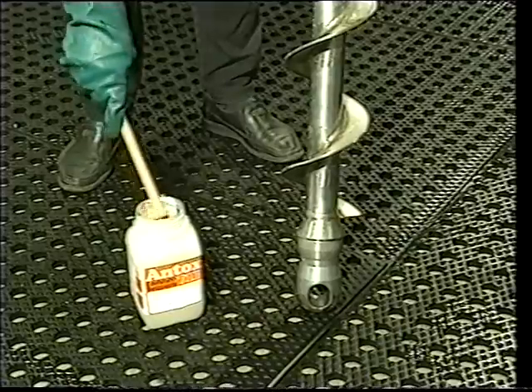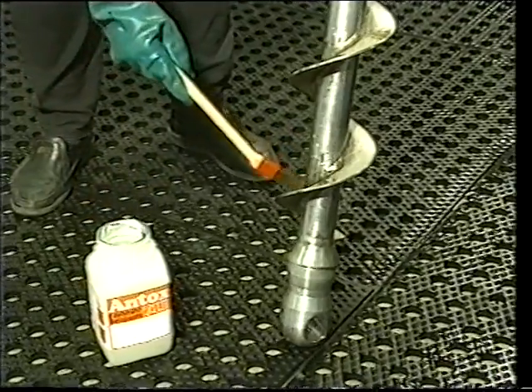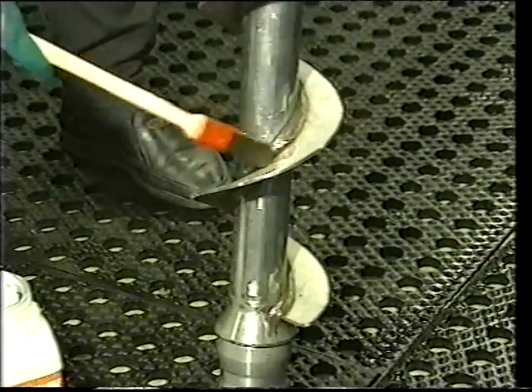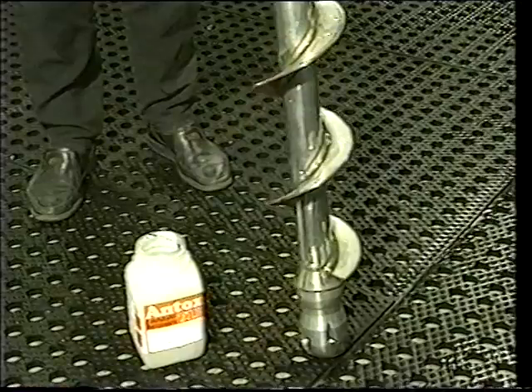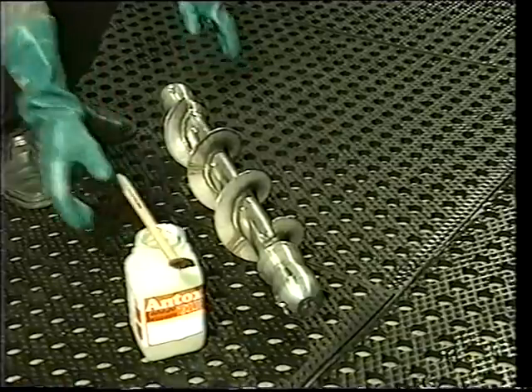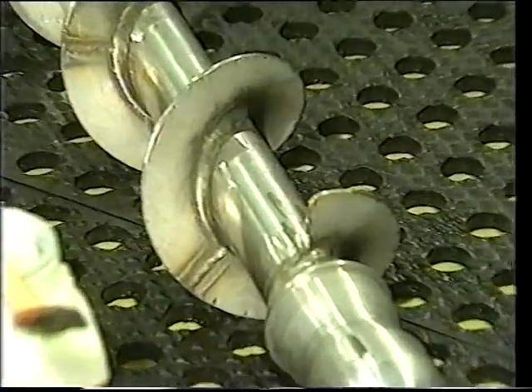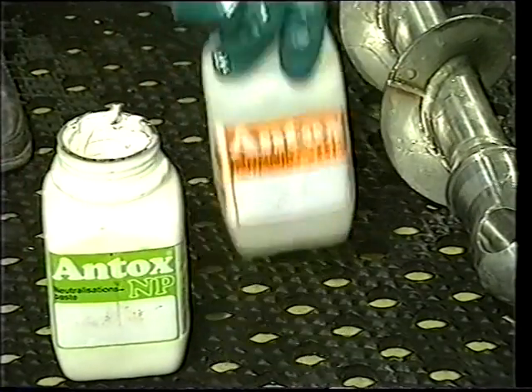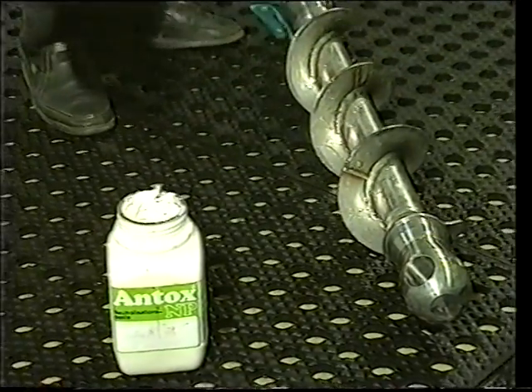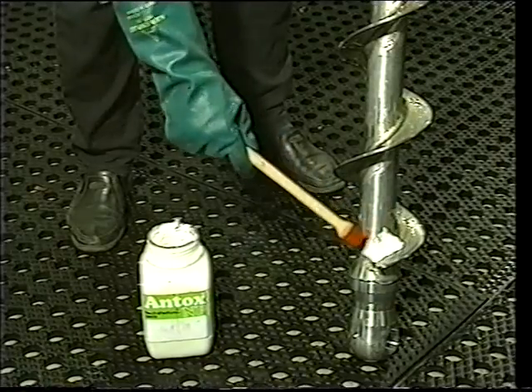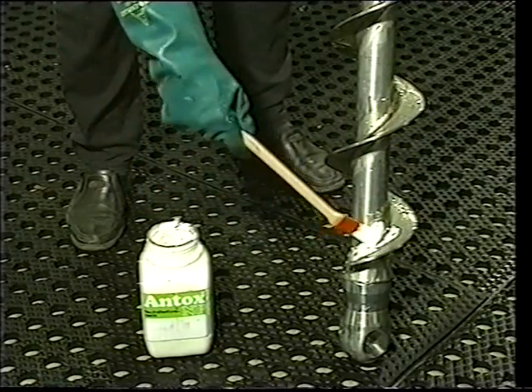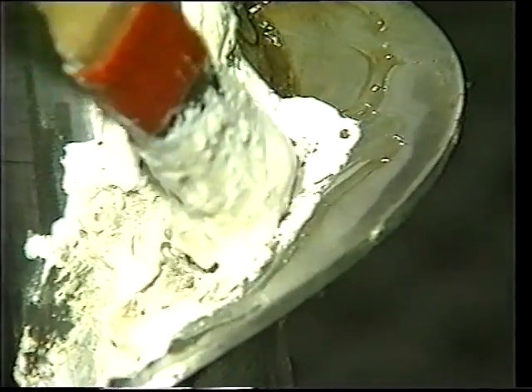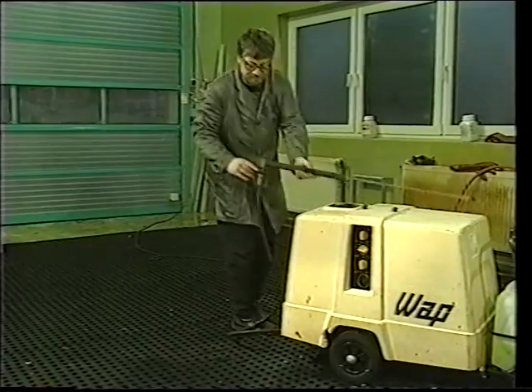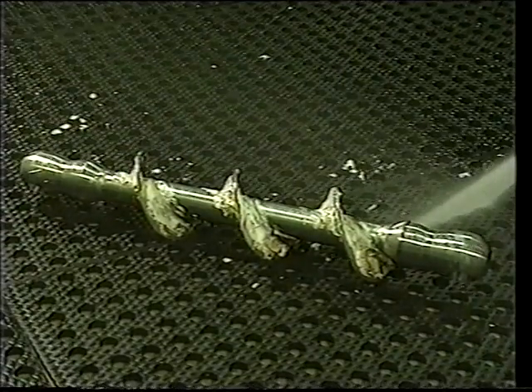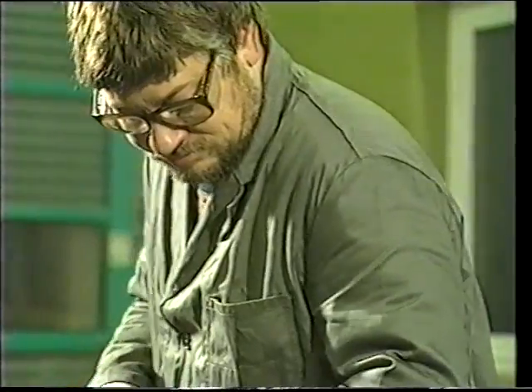One involves applying a pickling paste such as Antox with a brush. This cleans the weld and the adjacent heat-affected zone. Pickling time depends on the alloy, the temperature and the effectiveness of the pickling paste, but is generally about 1 hour. Antox NP neutralizes hydrofluoric acid in highly acidic stainless steel pickling pastes and binds heavy metals. Bubbling indicates the reaction between pickling residues and Antox NP. Finally, the treated parts are rinsed thoroughly with high-pressure water, removing all traces of scale and tarnish.